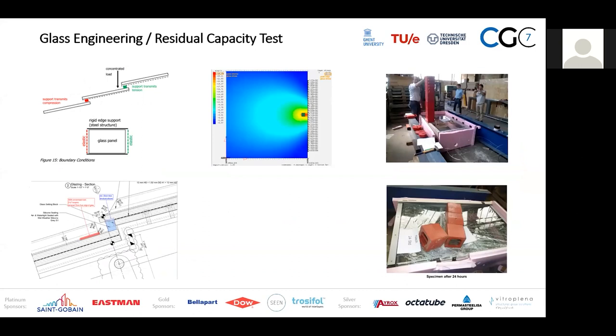As this is a glass conference, I thought it's good to talk a bit about the glass design. We had a relatively conservative approach that was coordinated with the city of Los Angeles. We were calculating the glass, which is two sides supported, with a point load of 150 kilograms on just 4x4 centimeters under 60 degrees Celsius, and had to prove in a test that in a broken condition the weight is not falling through and the glass is not cracking. By far we exceeded these requirements, also thanks to the structural PVB interlayer we were using.